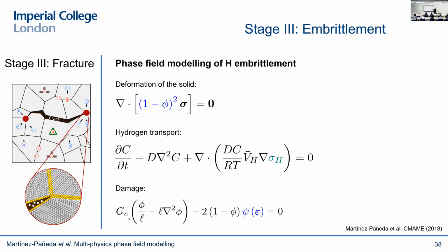Anyway, let me go back to the hydrogen. So we like to use phase fields. So we have, at the very least, in our problem, an equation for the deformation of the solid, another one for the diffusion of hydrogen, and another one for the damage process. And I'm showing here some of the couplings, but the key coupling, of course, is how hydrogen interacts with the damage process.